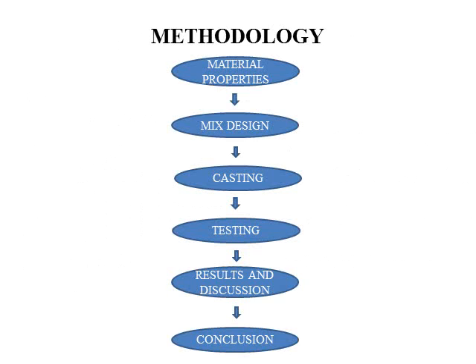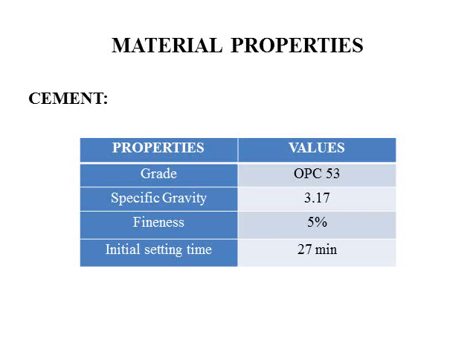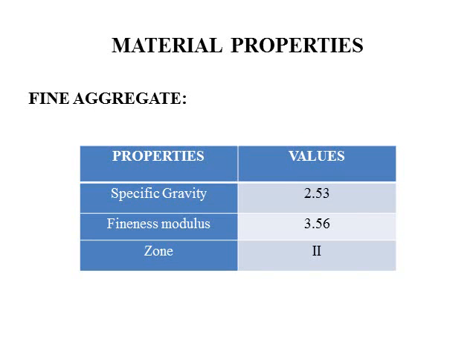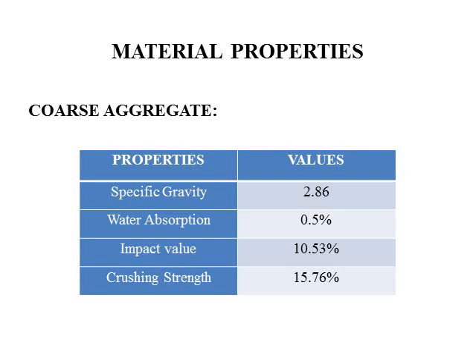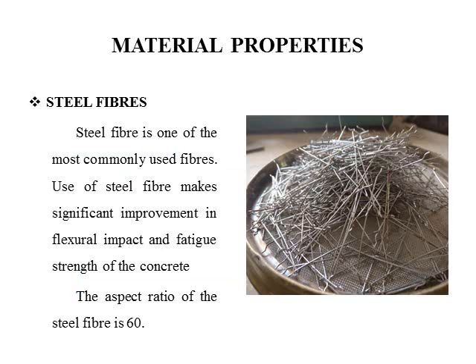Methodology. The methodology is as follows: material properties, mix design, casting, testing, results and discussion, followed by conclusion. Material properties. The properties of the materials used in our mix are shown. Cement. The grade of cement is OPC 53, specific gravity of 3.17, fineness 5% and initial setting time 27 minutes. Fine aggregate. Specific gravity of 2.53, fineness modulus 3.56, and it belongs to zone 2. Coarse aggregate. Coarse aggregate has specific gravity 2.86, water absorption 0.5%, impact value 10.53% and crushing value 15.76%.